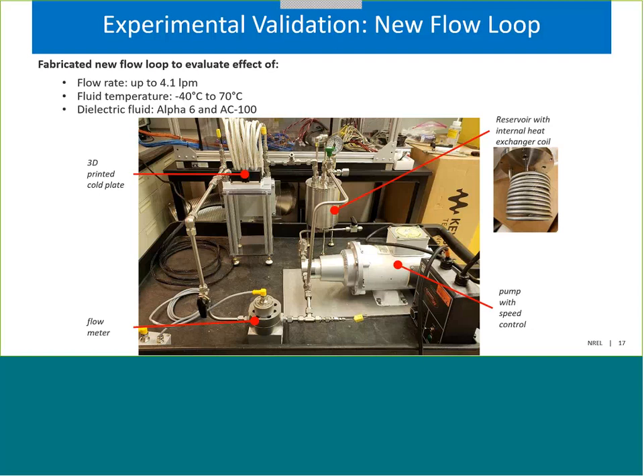And we're going to be looking at the effects of the flow rate. We want to conduct tests up to about 4 liters per minute. We'll probably take it up a little bit higher than that, maybe 5 liters per minute, just to see the effects. We also want to look at the effect of fluid temperature. So we want to look at temperatures from minus 40 degrees C, which can simulate a very cold winter condition somewhere, up to 70 degrees C. And then we're also going to be looking at different dielectric fluids. We're currently conducting tests with Alpha 6. We're also going to conduct tests with AC100, and we also plan to do tests with ATF as the coolant.